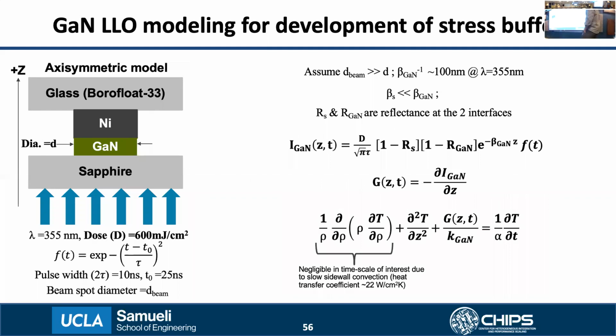So now what we can do is use this information to get the transient intensity variation in the GaN thin film as the incident light pulse strikes the interface, and that is given by this expression, which takes into account the transmittances at the two interfaces, the exponential decay of the light intensity within the GaN thin film, and also the temporal dependence. Once we have this transient light intensity variation within the film, by taking its gradient along the z direction, we can get the heat generation rate, which can then be substituted within the heat transfer equation to solve for the temperature transients at the interface.